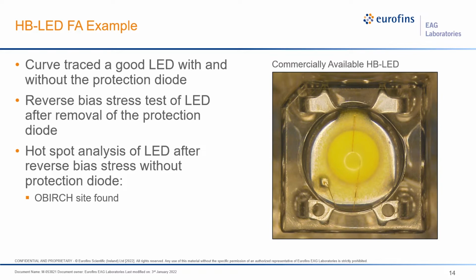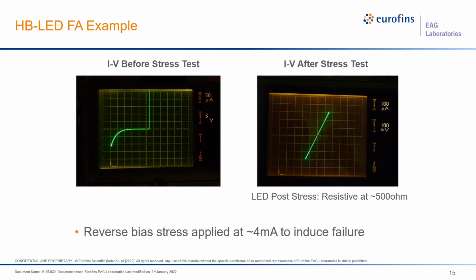So in this case, we take this common LED, we do some IV characteristics tests before, showing that we have good diode behavior. We actually remove this protective diode here and then apply a large reverse bias at high current to kill the device, and then we find that we have a shorted device that has ohmic behavior after the test.